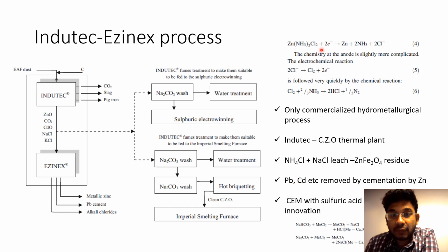Here we go. So the one thing that they tried here is that they were struggling with the fact that when you use chlorides, instead of oxygen evolution at the anode, you have chlorine evolution at the anode, right? And once you have chlorine evolution, it's not so bad, some chloralkali plants can handle that. But in reality, for recycling plants to handle chlorine evolution is difficult because the anode lifetime will decrease. It's a very intense process, and it's not so easy to have a stable anode over a long period of time. Then you have to opt for a very expensive anode, and that's a problem altogether.